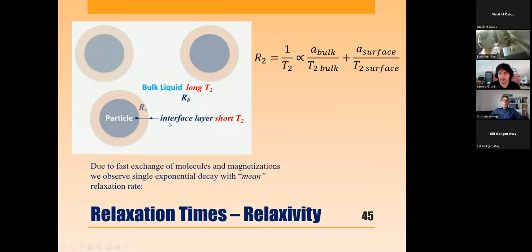When you have particles and you have the solvent that contains these particles, and you look only at the relaxation of the solvent, the solvent around particles is interacting with the particle, forming a so-called interface layer that is somehow adsorbed around the particle. The molecules of solvent that are adsorbed, of course, have much less mobility, and we discussed that the lower the mobility, the lower T2, the lower relaxation time; the higher the mobility, the longer T2. So for the bulk solvent you have the long T2, and for those nearby a particle, they have short T2. And this model works quite nicely until some considerable concentration of particles.